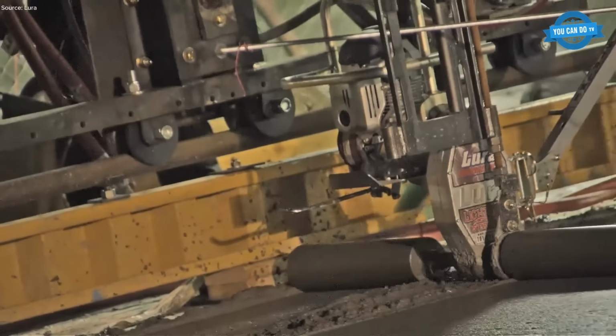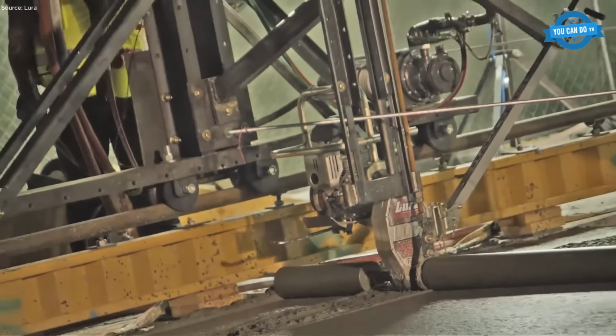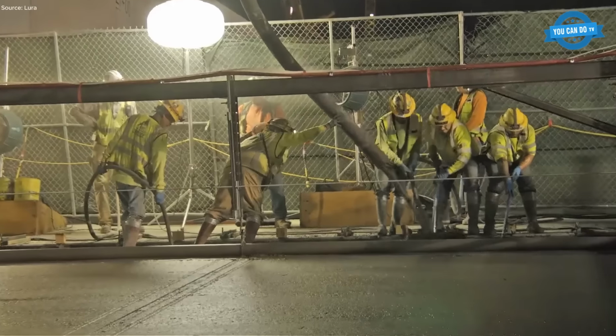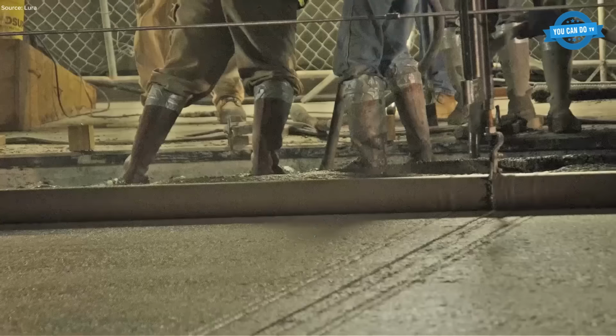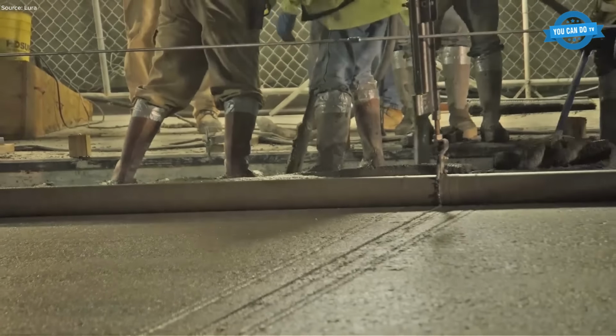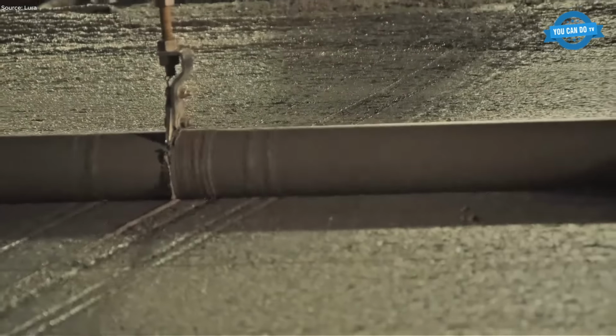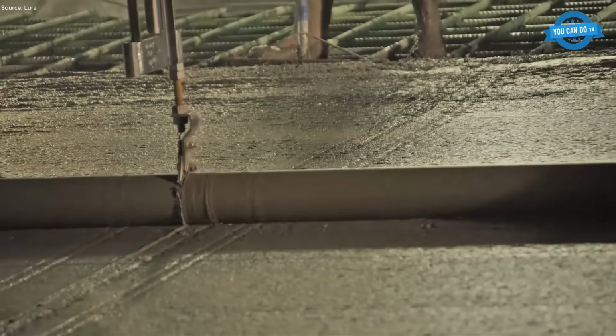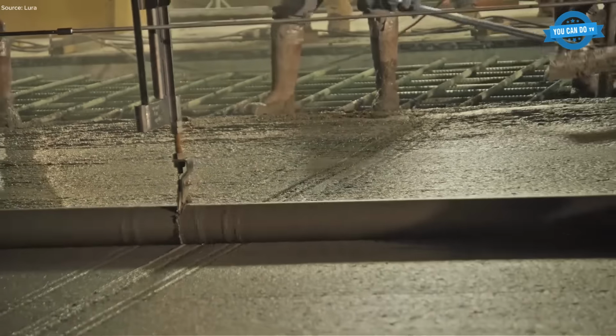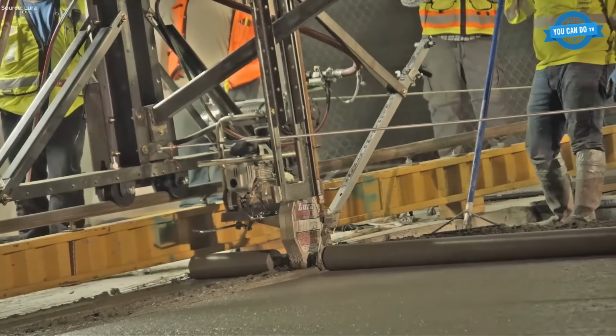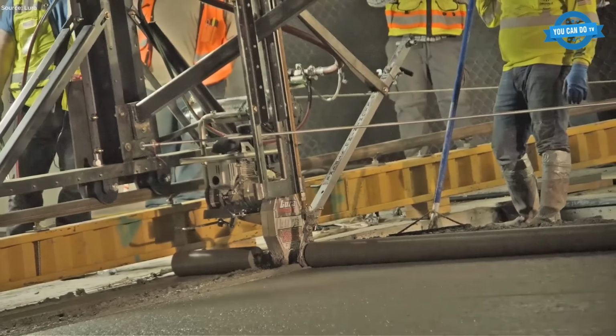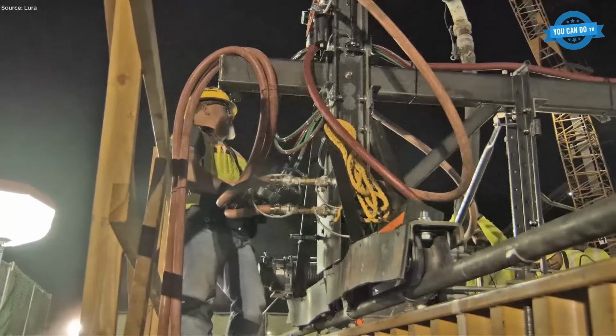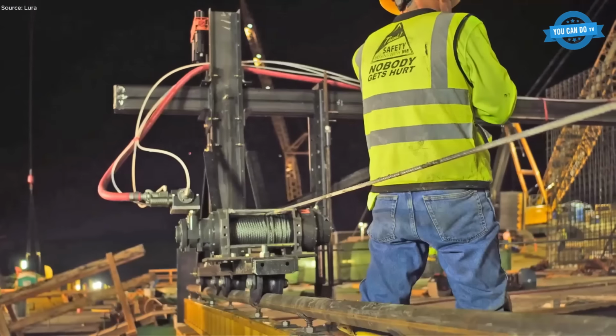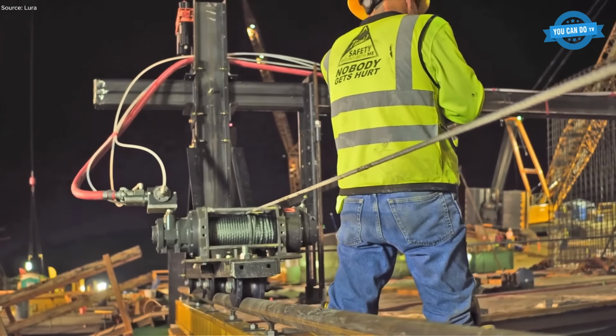The lower spillway posed the greatest engineering challenge, a steep 4-to-1 slope requiring concrete placement across a 37-foot width with less than a quarter-inch tolerance. Traditional vibrating screeds were unsuitable on the incline. Instead, a specialized roller screed and trolley system was deployed, enabling uphill finishing without vibration, maintaining alignment, surface uniformity, and long-term structural performance under extreme hydraulic loads.